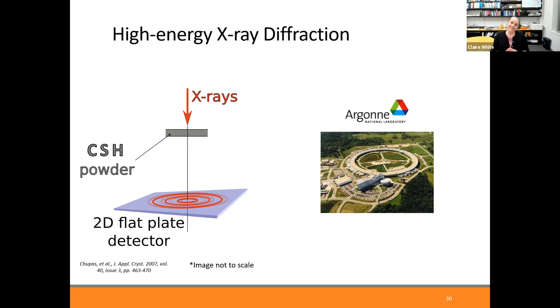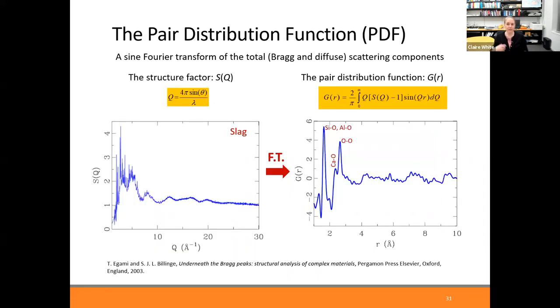What it is that you're using the high brilliance of the X-rays from the synchrotron to scatter from your sample, which means that you're getting a lot more X-rays being detected, which leads to higher resolution data. It also means that, depending on the energy of the X-rays, you can get different 2-theta coverage of your X-ray diffraction pattern, which means that you can do Fourier transforms of your diffraction data and look at the data in real space.